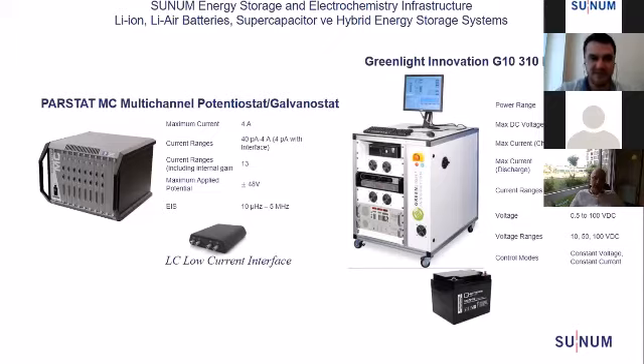And this system is also combined with the electrochemical impedance spectroscopy method. With that method, the ohmic resistance of the electrolyte or membrane of the battery can be screened, and the charge transfer capability of the anode material or cathode material can be realized with that measurement technique.